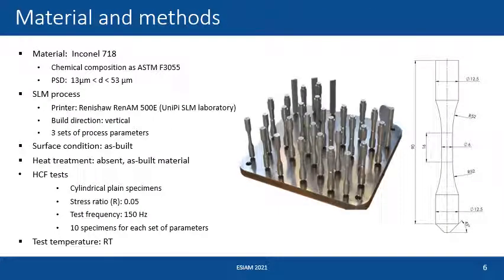It was used a standard Inconel 718 powder for selective laser melting, featuring a particle size distribution comprised between 13 and 53 microns. All the specimens were printed by using the Renishaw RenAM 500E printer that is installed at our university, and all the specimens were printed in vertical direction. Three sets of process parameters were employed, so baseline, A1, A2. All the specimens were tested in the as-built condition, both for the surface condition but also about heat treatment. The heat treatment was absent. We test the specimen in the condition exactly after printing.